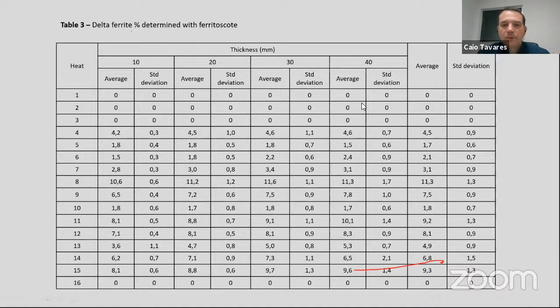We have some heats, those three first heats, we didn't have any ferrite content, was 0, no sample. And the last one also. And those other ones, we got different ferrites. We see here the average of heat thickness, here the average with 10 millimeter, with 20, 30, and 40, and the standard deviation that was observed in each thickness. So, as I made several measurements in each thickness, we got the average and standard deviation.